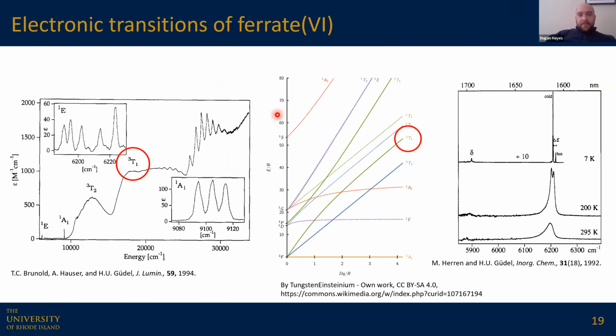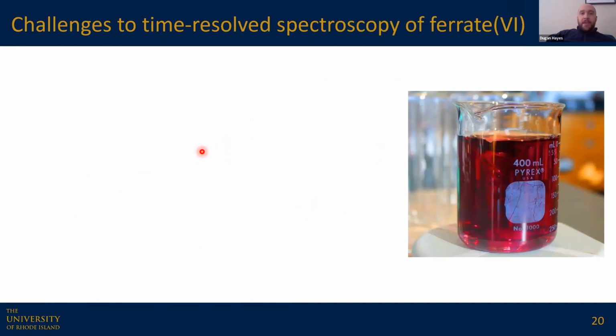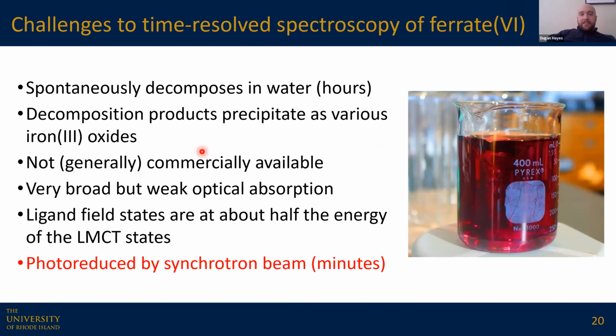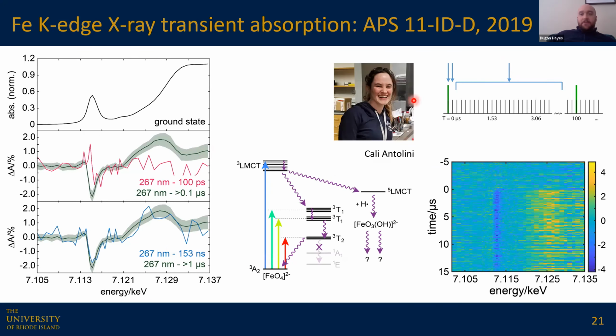And skip this, other than to say that the optical absorption spectrum of ferrate actually matches the Tanabe-Sugano diagram very well, which makes it easy for us to analyze our signals and also be able to pump into these individual bands and watch the kinetics from there. So there's lots of challenges associated with it that probably explain why no one had done this in the past, but we went ahead and did it in that same beam time. This was work led by my student Cali Antolini, and this is what we were able to see at 11 IDD. We got these really terrible looking single pulse, single probe pulse X-ray transient absorption spectra at 100 picoseconds and 153 nanoseconds, but we could average a lot together on the microsecond time scale to get better signal to noise and see that the 150 nanosecond spectrum looked more or less identical. So we weren't seeing too much activity in terms of evolution after 150 nanoseconds.